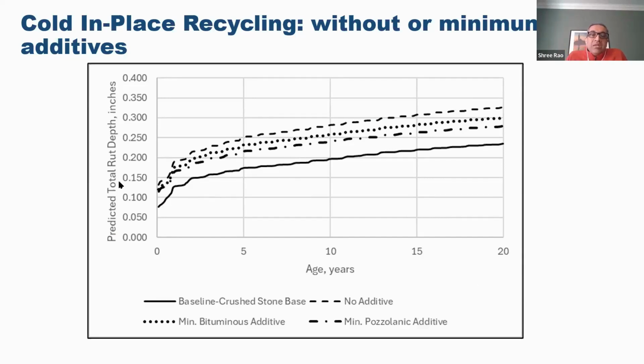So let me start with the rutting. The baseline design has this level. If you don't have any additives, you have a higher level of rutting. If you have a minimum amount of additives, the bituminous additive, you have this level of rutting. And if you have pozzolanic additives, it's a little better. So at age 20, obviously, this dense graded design with the crushed stone base has the lowest rutting, and the cold in place recycling has a little bit more rutting depending on the amount of additive.